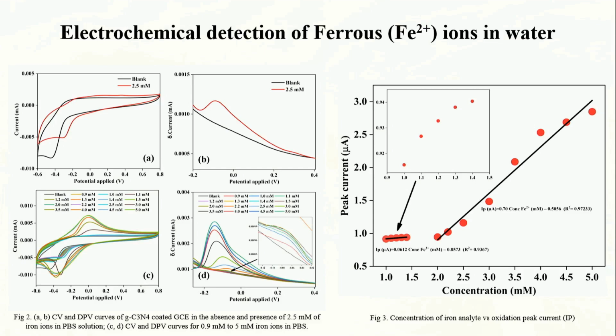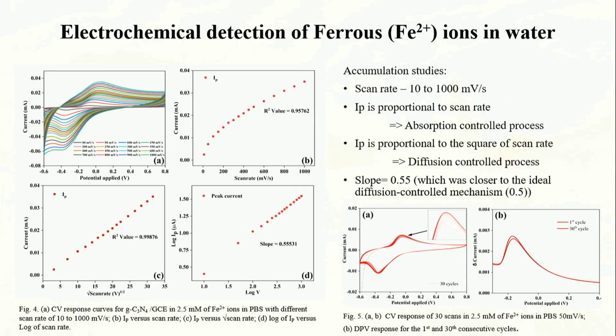Here it forms an adsorption controlled process, and after some time, at a higher concentration, it is more of a diffusion control process. In order to confirm this, we ran a scan rate study. We ran the CV for 2.5 millimolar ferrous ion at different scan speeds, from 10 millivolt per second to 1000 millivolt per second.